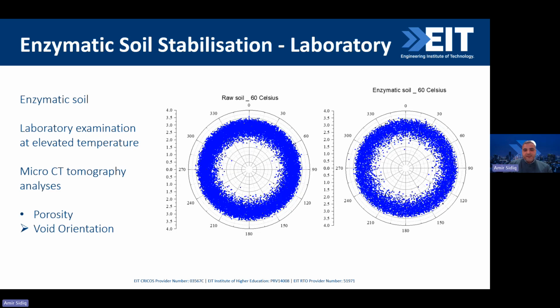Then at 60 degrees, you can see it's actually increasing even further for the raw material, but for the enzymatic, it's actually reducing. So this again really represents the control of the enzyme material. It's actually controlling the shape, the orientation, the porosity content, and the different shape parameters, such as structure index and model index of the void within the sample.